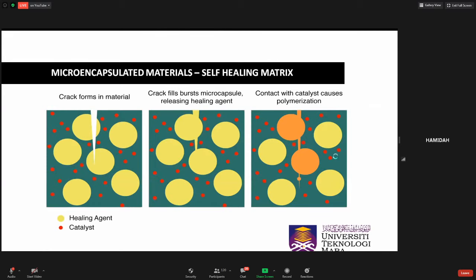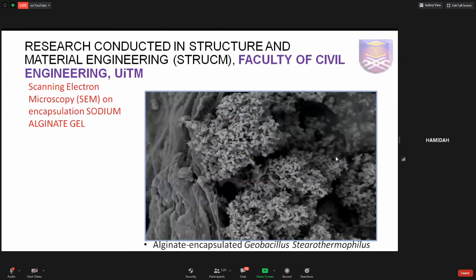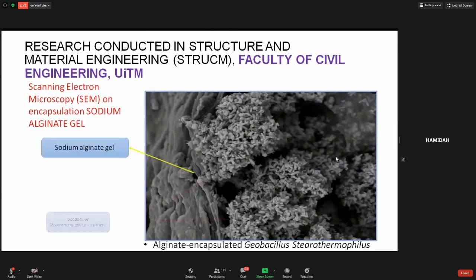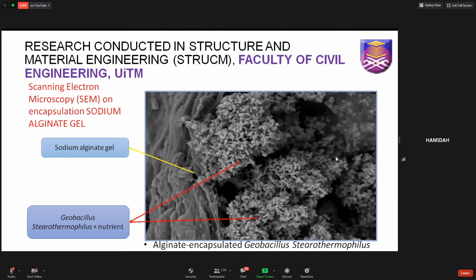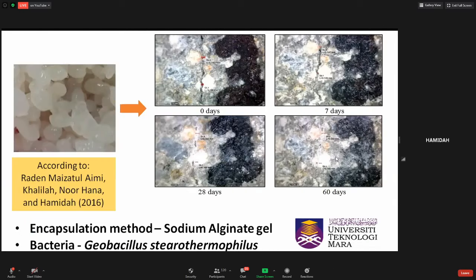Research has been conducted in the Faculty of Civil Engineering, Universiti Teknologi Mara, on self-healing concrete using Geobacillus stearothermophilus encapsulated in alginate gel. The encapsulated bacteria was mixed in concrete and then artificial cracks were introduced. It was observed that the cracks will fill up in 60 days. The study showed that encapsulated bacteria can heal the maximum crack width of 0.97 millimeter as compared to direct incorporation of bacteria. Smaller crack width only can be filled up.